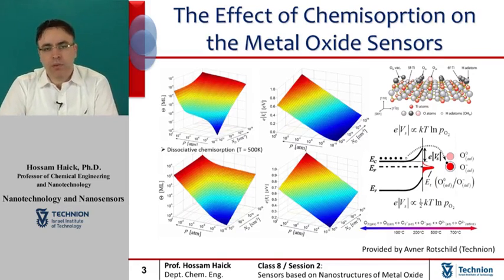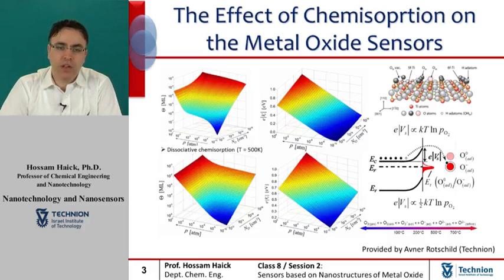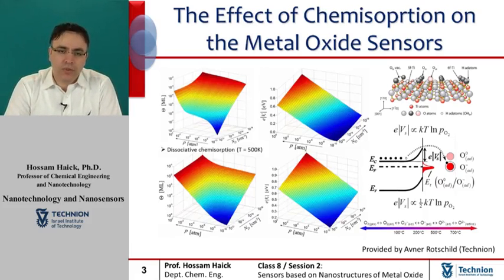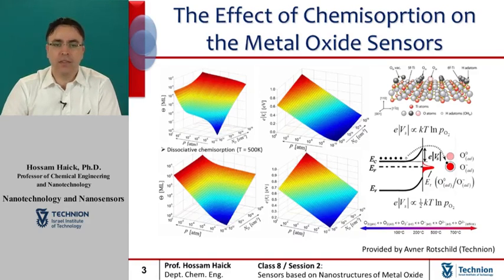The most important parameter here is the energy level of the surface adsorbates. In this context, I'd like to draw your attention that researchers treat species as unoccupied and occupied surface states, respectively, and calculate their fractional coverage using the Fermi-Dirac distribution function.